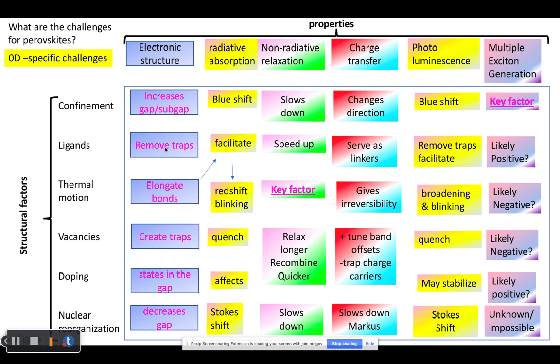Ligands are expected to remove traps, facilitate radiative absorption because they push charge carriers inside the nanostructure. They speed up non-radiative relaxation because they add additional degrees of freedom with different frequencies. For charge transfer, they may serve as linkers. And for photoluminescence, they are also favorable because they remove traps. Nothing for the rest of the structural factors, nothing is known for multiple exciton generation because it is an extremely expensive calculation, about a year, or maybe half a year in the most favorable case, for a single model.